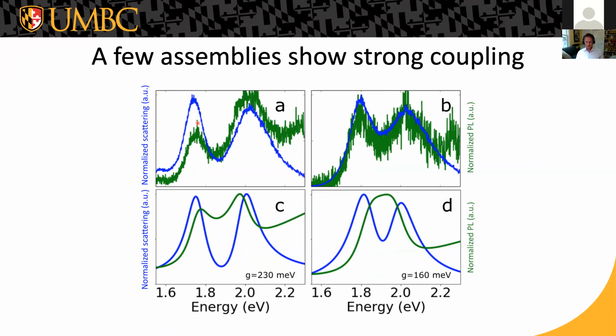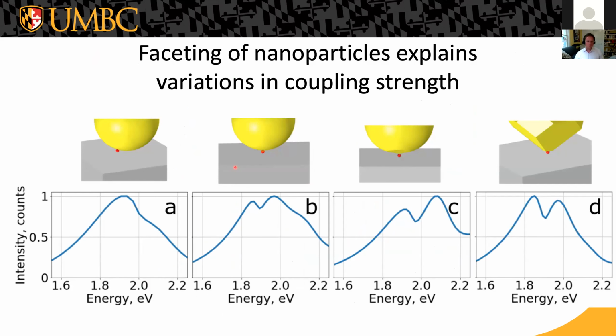So, one obvious question is, why do we see different coupling strengths in different configurations, right? And why is it only a couple of percent of the time that we get into the strong coupling regime, and only a little bit more often that we get into the intermediate coupling or induced transparency regime? So to understand that qualitatively, we turned to finite element calculations. These don't reproduce our experimental spectra quantitatively, but they do show the same trends.